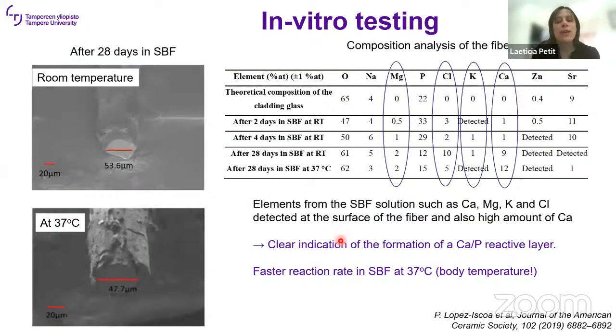So we used EDS, so energy dispersive spectroscopy, to analyze the surface of the fiber. So here you have the expected composition for the cladding, and then the composition of the cladding after 2, 4, and 28 days in SBF. And we notice the presence of magnesium, chlorine, potassium, and calcium at the surface of the fiber. And these elements are actually the ones from the SBF solution. So this is a clear sign that we have this hydroxyapatite layer, so this calcium phosphate reactive layer, confirming that even if we added some zinc and strontium, the fiber is still bioactive.